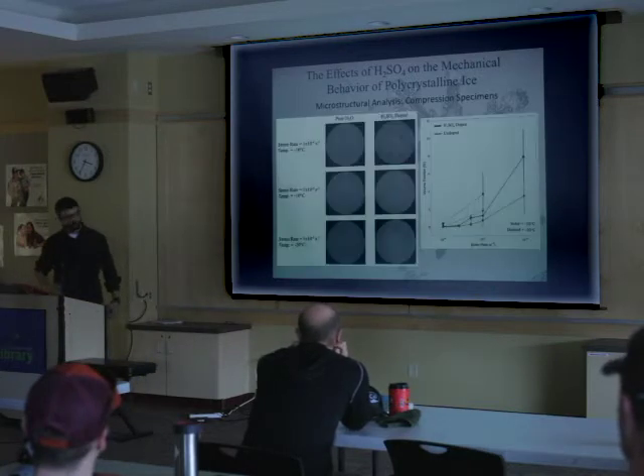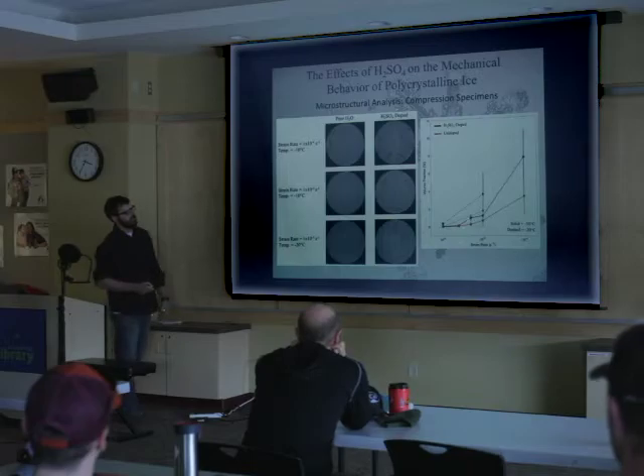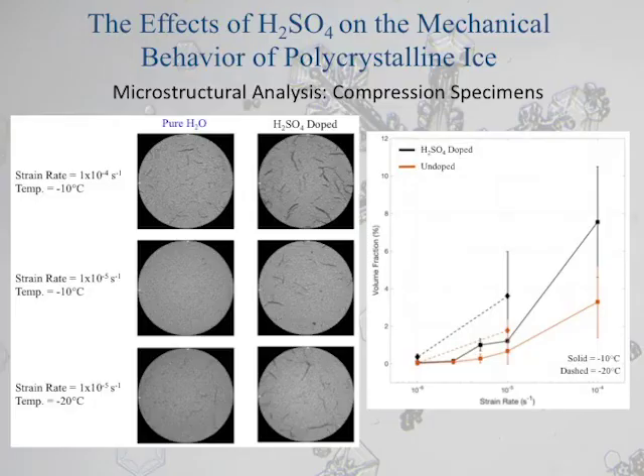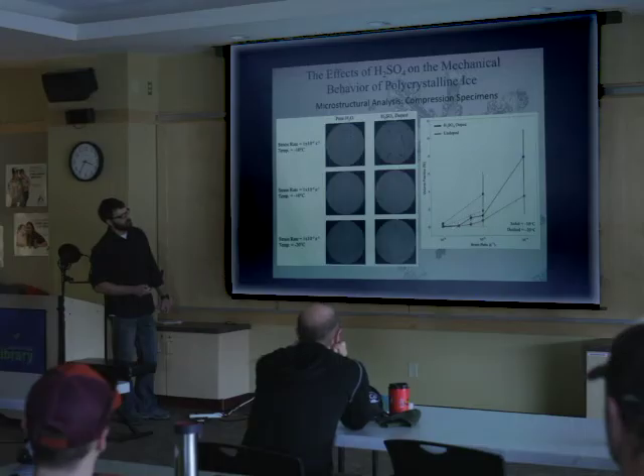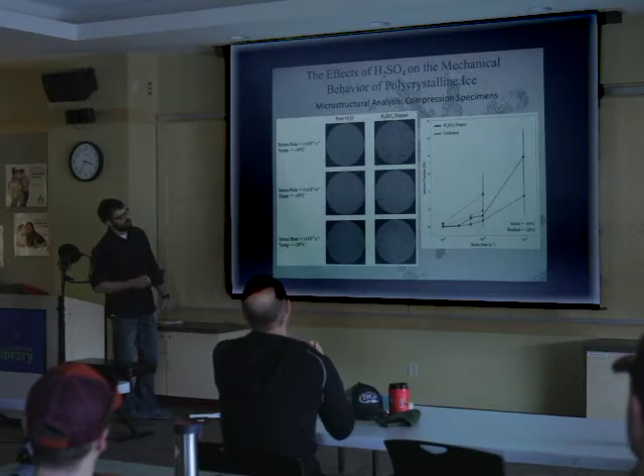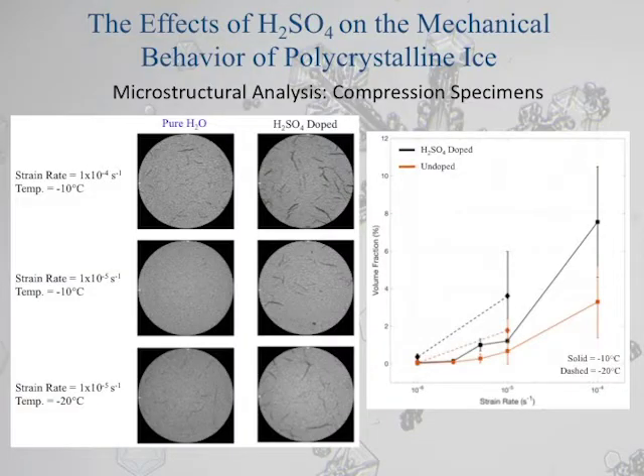When we plot that up, what we found was that the sulfuric acid doped ice started cracking sooner. The sulfuric acid doped ice is the black line, the undoped ice is the orange line, and we're moving up to faster strain rates here. Then we have the volume fraction, or more or less the number of cracks, on this axis. What we saw was that the sulfuric acid doped ice not only had more cracks in it, but started to crack sooner than the undoped.